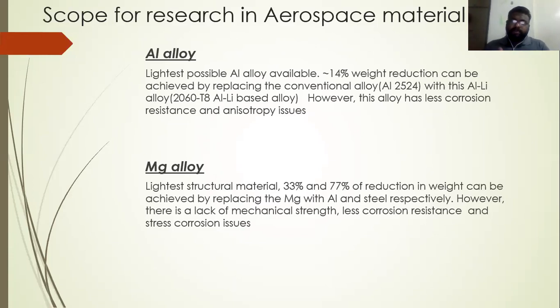So we'll see material by material, in each material, what problem it has and what could be the possible solution. Let's see. First thing is aluminum alloy. It is the lightest possible alloy, there is no doubt in it. About 14% weight reduction can be achieved by replacing conventional alloy with the aluminum lithium alloy. Even in aluminum alloys, the aluminum lithium alloy is the lightest one. Almost 40% reduction in the weight can be achieved by replacing the conventional alloy with aluminum lithium. However, this alloy has less corrosion resistance and anisotropy. So if people start working on this issue, that will be a good chance for ending up with a good research or very interesting outcome.